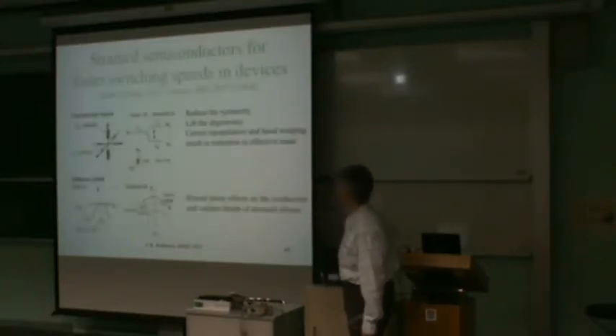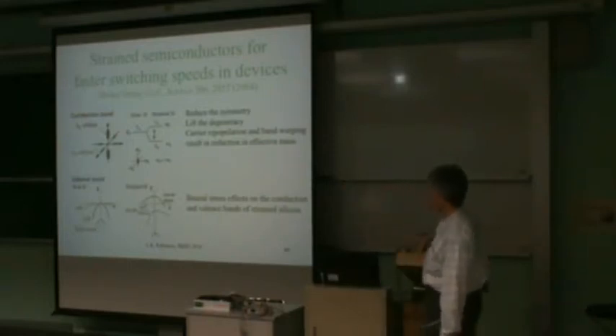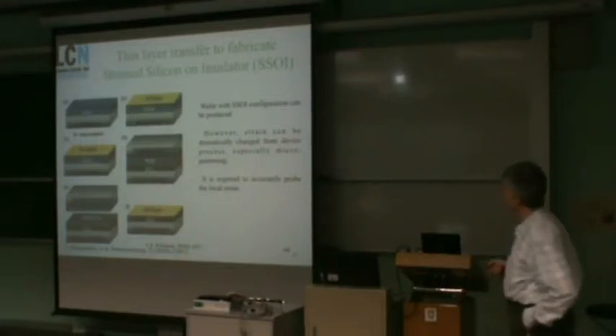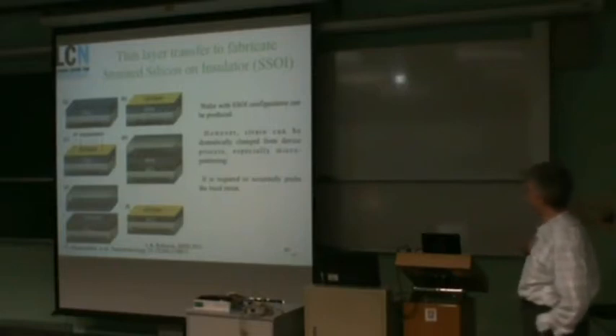All right, so this is what we're looking for. We're using SOI, particularly strained SOI. We can adapt the band structure for improving the mobility of the carriers. And we've worked out a method. Actually, this, I guess, is an industry standard method, but by collaborating with a group in Germany, we were able to get hold of some strained SOI.